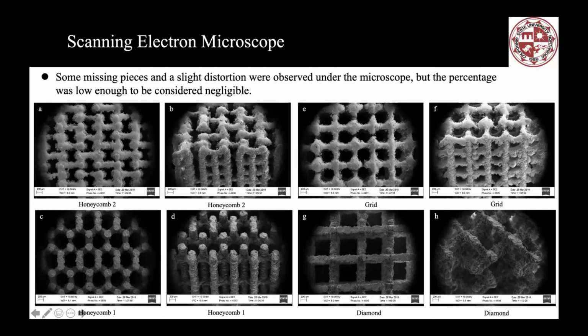So this is good for the bone implant. But here you can see some of the percentage missing. You can see some missing pieces over here, and some of them have either missing pieces or slight distortion. The shape is not as perfect as the one we designed in the CAD model, because for metal 3D printing, each layer is like 40 micron. After the slicing, they will lose some information. For the printing, they only print layer by layer, so they can only get the accurate information on each layer, and then the next layer will be different. They will miss some information between these layers, like 40 micron. So that's the reason for some missing pieces and slight distortion.